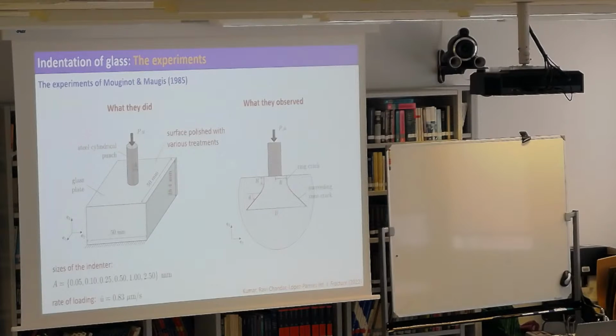And then what I'm going to show you is comparisons of their measurements for a number of these quantities with the theory. We need to calibrate the theory. This is very important. Calibration of the theory means that you need experiments. And believe it or not, there are not so many things you can use to calibrate. Elasticity, no problem. They actually did some ultrasound measurements by which they measured very accurately the elastic constants of their borosilicate glass. So this is the Young's modulus, that's the Poisson's ratio.